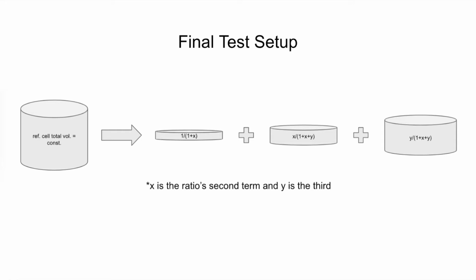It worked similarly to the 2-cell test, and we found an ideal ratio of 1 to 2 to 4, meaning the smallest cell was 1/7 the sample cell volume, then 2/7 the volume, then 4/7 the volume. This gave us 100% of the points under the maximum desired porosity and almost 100% under the precision. Only the smallest of the samples were affected, and their precision wasn't too far above the desired value, so we decided to use this design and iron out the wrinkles in prototyping.